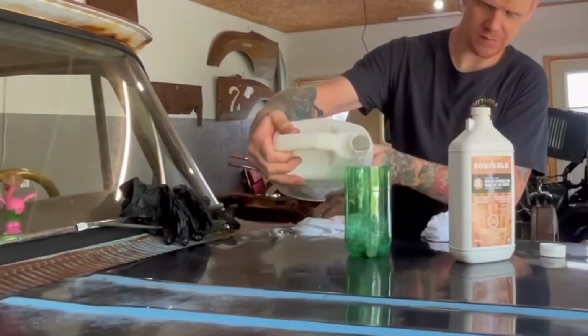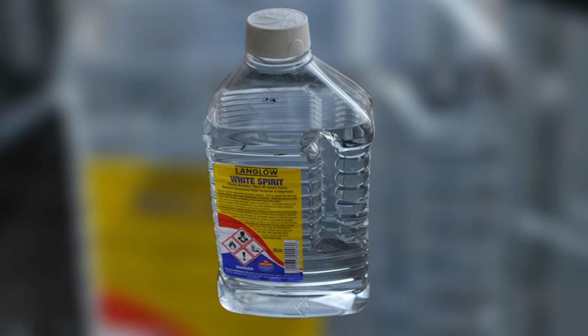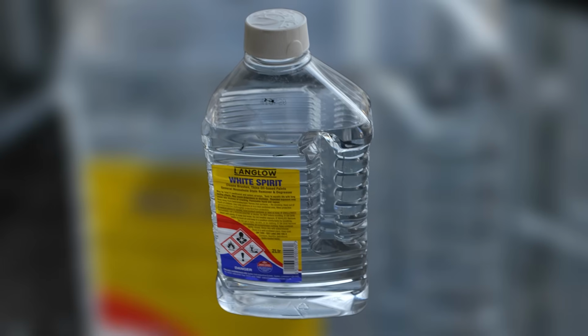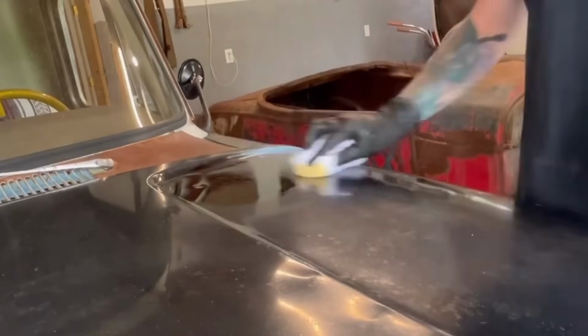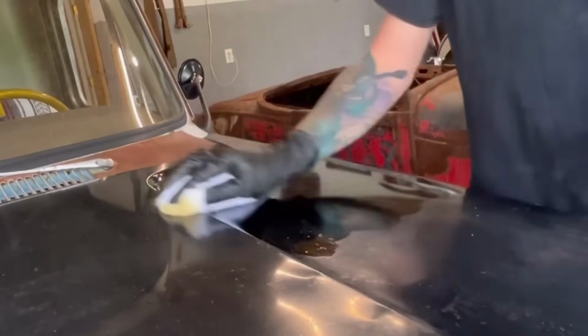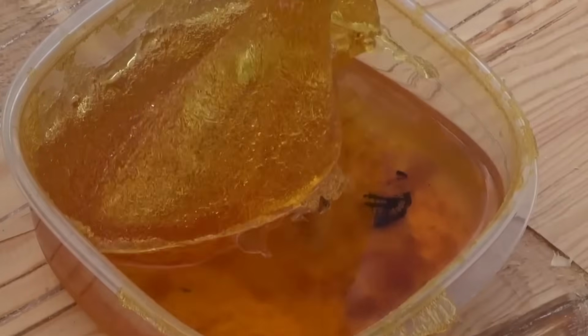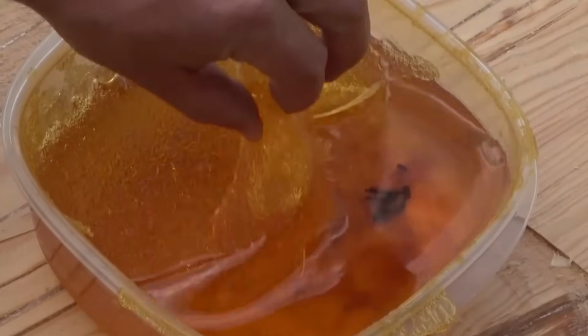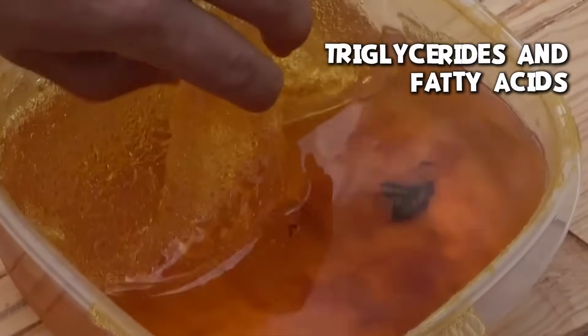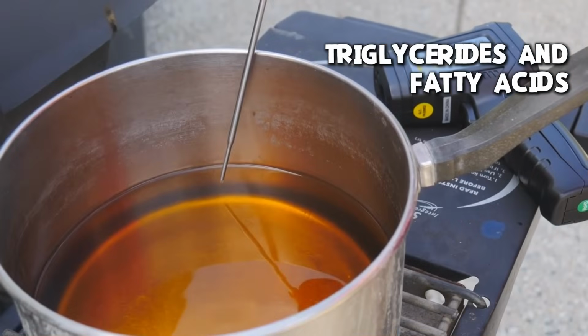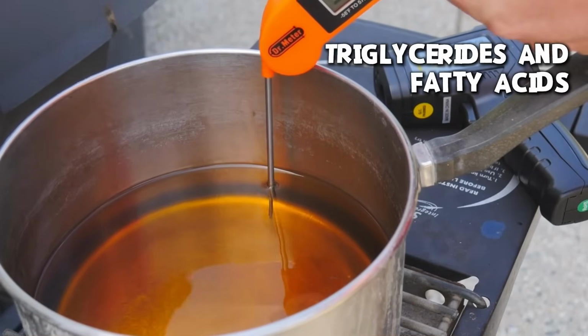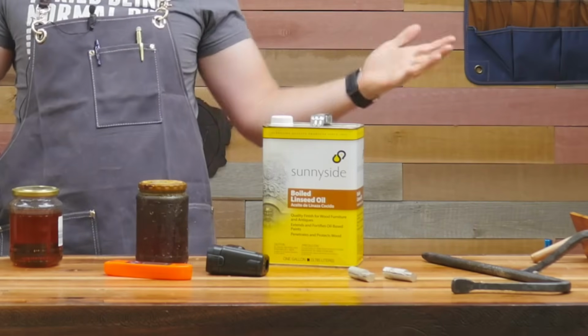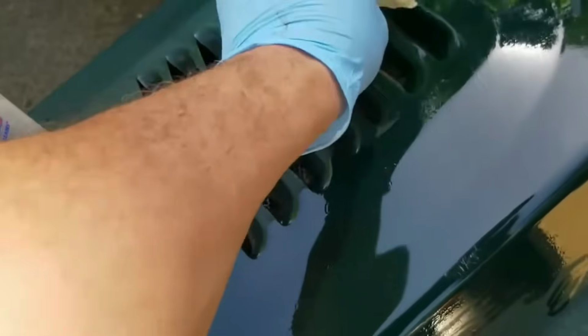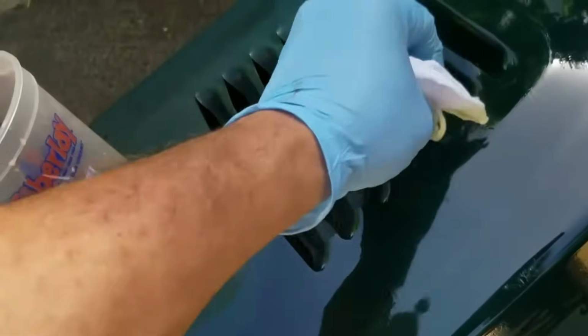The paint thinner in the mix, mineral spirits, also called white spirits, acts as a carrier solvent. It temporarily softens the very top layer of the oxidized plastic surface, opening up the polymer just enough to allow what comes next to get in. The linseed oil follows the solvent in, carrying with it a complex mixture of triglycerides and fatty acids that are chemically similar to the plasticizers that were originally built into the material. It is not coating the surface, it is replenishing what was lost. When the solvent evaporates and the linseed oil cures, it cross-links with the polymer structure and stays there.